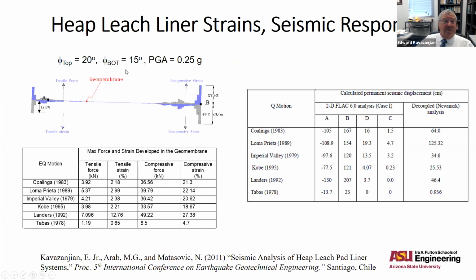Interesting, even when we had a case where the peak ground acceleration exceeded the yield acceleration of the geomembrane, we still got significant tensile stresses in the membrane, belying this philosophy that if we have that lower interface strength on the top, we're not going to have any tensile strain, mostly due to the anchoring of the geomembrane. You know, so the geomembrane is rigidly anchored, typically by an anchor trench at both sides. And so as it stretches in response to the shear stresses, even below yield, it does induce tension in the geomembrane.